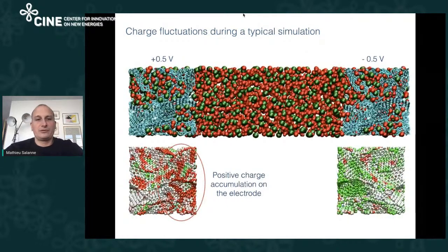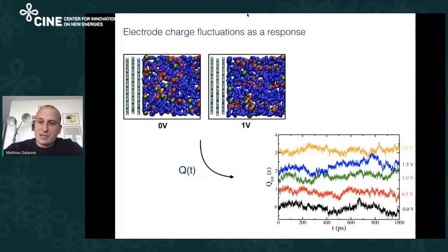So as you can see, during the simulation, we have access to the charge fluctuation. And so in fact, we use this as a response. This is something that would be very difficult to have access to from an experiment. So we change the potential of the electrode and we look at how the charge is changing. And from these changes in charge, we can get a lot of different answers. This is something really interesting because we can now link the charge inside the electrode to the behavior of the liquid, and we can see whether some structural arrangement inside the liquid generates a better charge or not. And so we can propose solutions to improve capacitors like this.